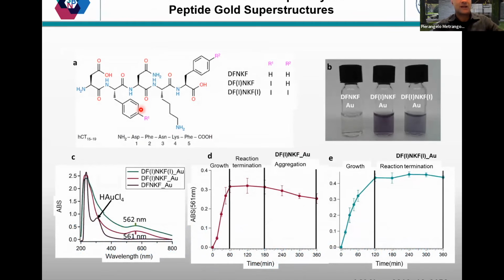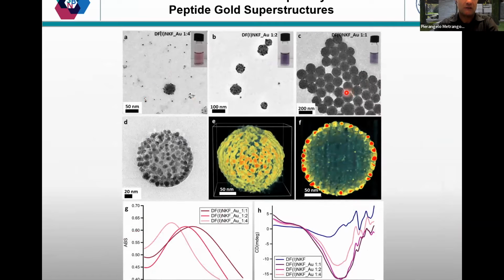Introducing halogen atoms into peptides also lets you introduce new functions. For example, we use these diiodo peptides for mixing with gold, and without any iodine, no reaction occurs. Whereas with iodine, by simply mixing one equivalent of gold chloride plus one equivalent of the peptide, heating at 60 degrees for half an hour, you get these purple solutions, where if you look inside with a microscope, you see very complex objects. In this case, we have roughly 50 nanometer supraparticles, made of peptides inside, fully decorated by gold nanoparticles on top.